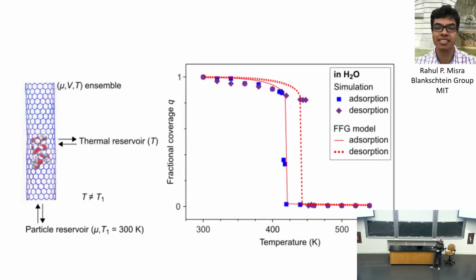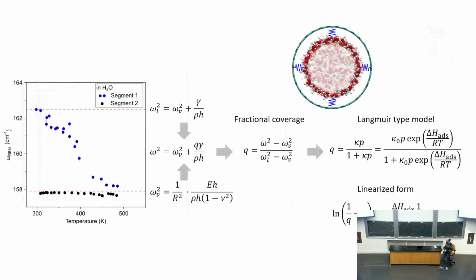And to understand this a bit from a theoretical side, we did grand canonical molecular dynamics simulations where we couple this open system here to a particle reservoir and then a thermal reservoir. Actually different, because in our experiment we do only local heating. So this was an innovative approach to have two reservoirs here, particle and thermal, which are different. And the behavior we get looks a bit like this. And it's suggested that indeed it can be reproduced by adsorption-like physics.